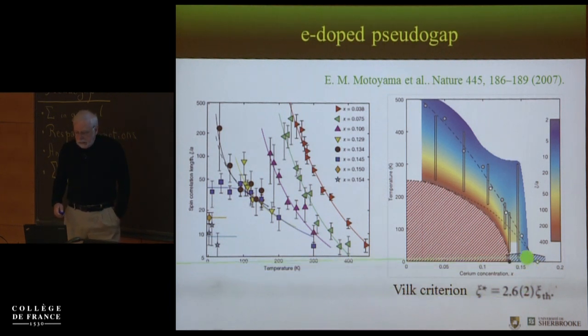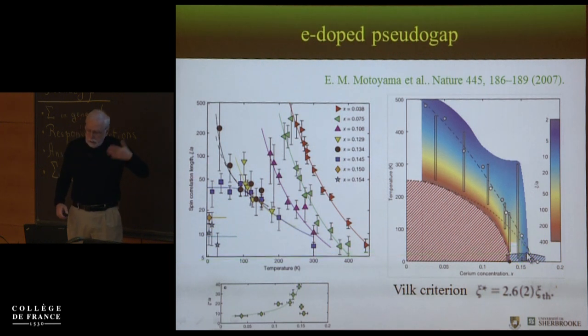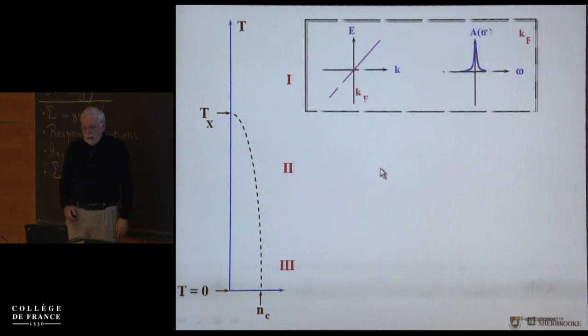But where things stop working is here near optimal doping. You see, near optimal doping, the correlation length goes down again. In fact, if you draw it, it's like this. So it's as if, when you get close to the superconducting phase boundary, there's an interference between superconductivity and antiferromagnetism, which is not taken into account in this theory. That's one possible explanation. The other one is that there's something wrong with the experiment, but I wouldn't dare say this. So the physics is simple to understand.